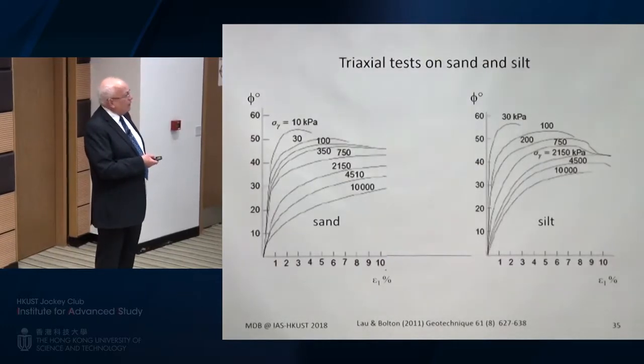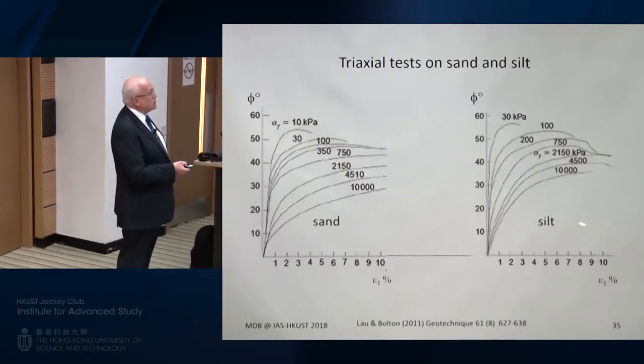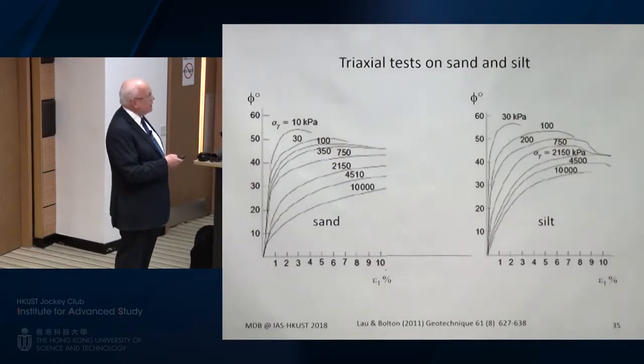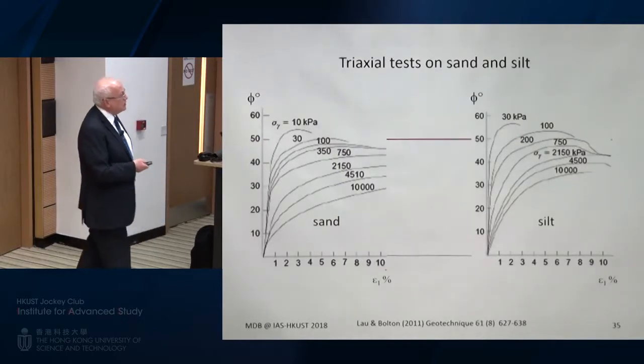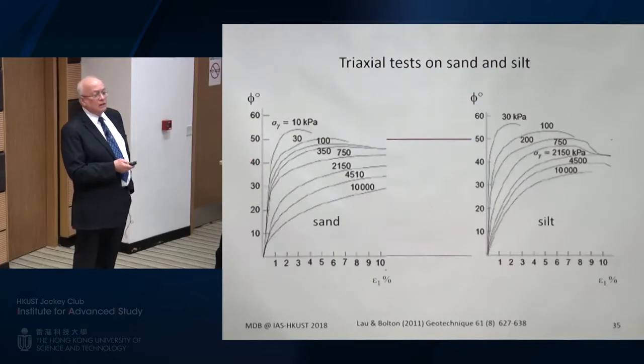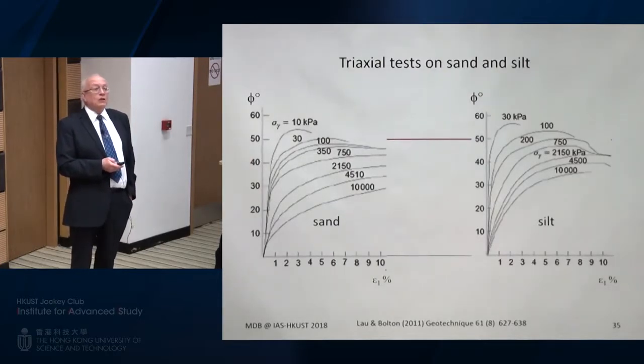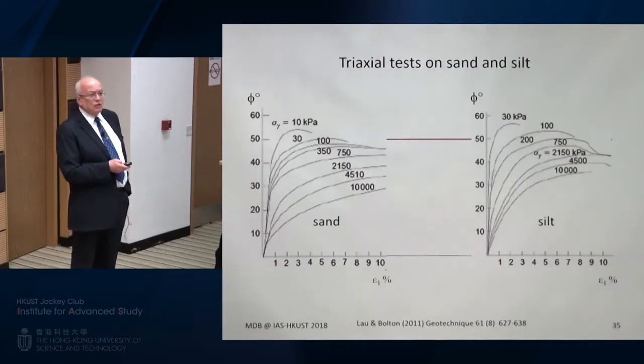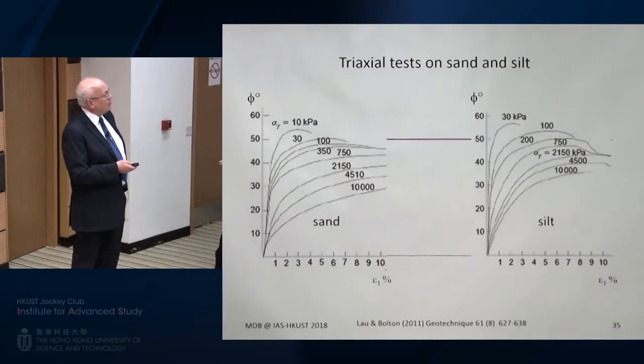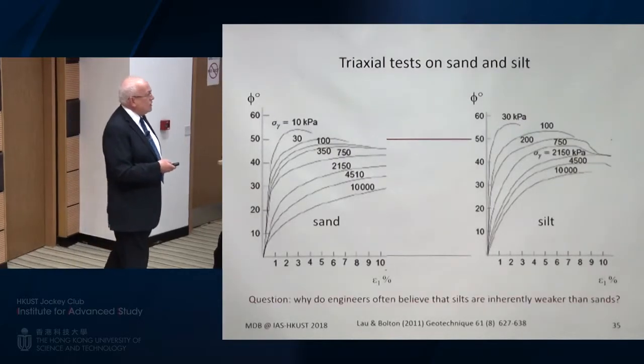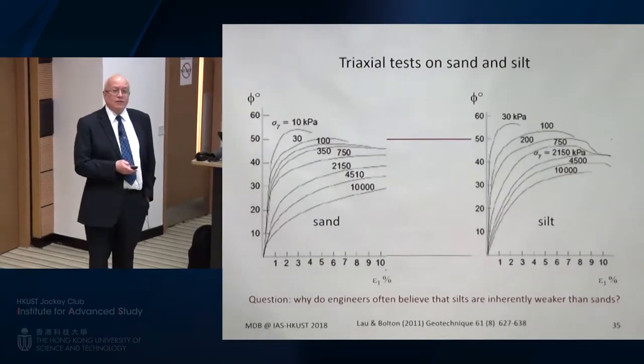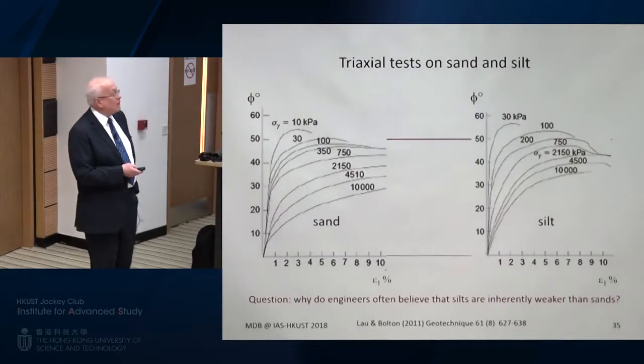And he did his own triaxial tests at a very broad range of stresses. So there's the sand on the left and the silt on the right. And if you look at it, compare, for example, 50 degrees of angle of friction, you'll see that the silt is a little bit stronger than the sand. Does that mean we've gone wrong somewhere? Well, no, it's inevitable, because silt is stronger than sand, and so it's more dilatant, as you can see at every point. It's intriguing that engineers always think that silts are weaker than sands. I'll just leave that one with you.